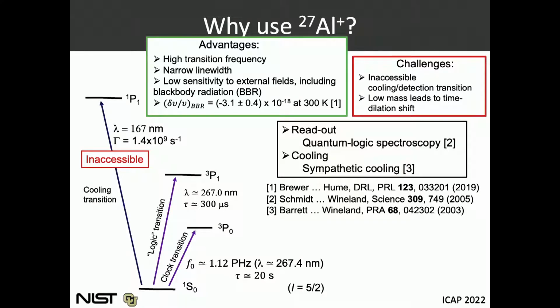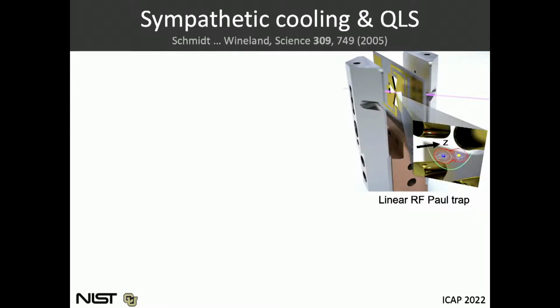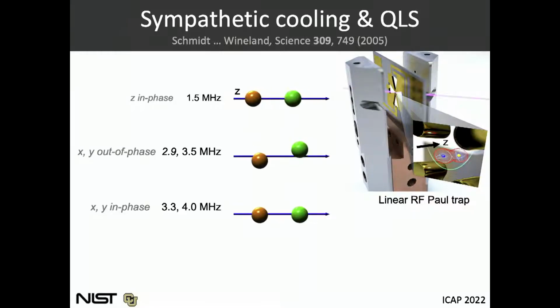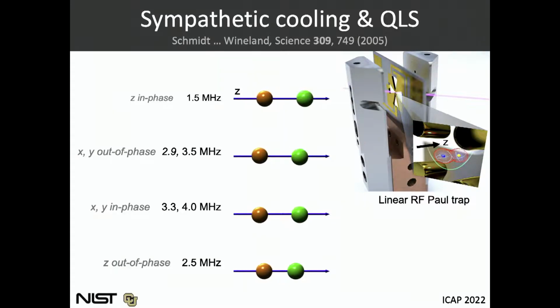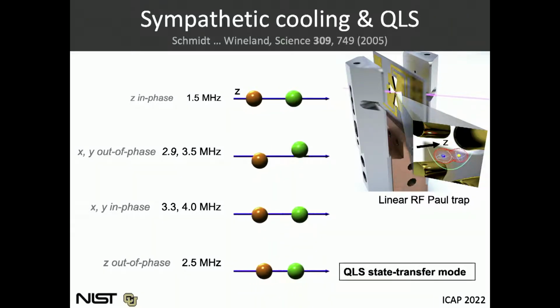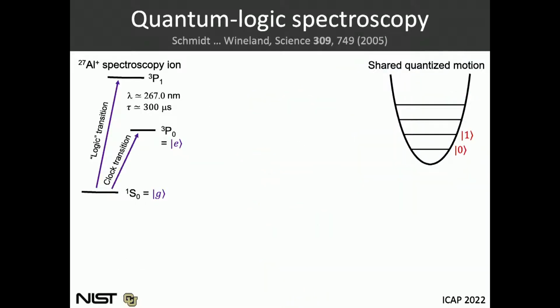Instead, we're using techniques from quantum information where we co-trap an aluminum ion here in the same trap with a logic ion that will be either magnesium or calcium for the clocks I'll talk about today. And because these two ions are both positively charged, their motion is strongly coupled, and we can laser cool the magnesium in order to cool the motion of both ions. And furthermore, we can use these motional modes, which are quantum degrees of freedom, to read out the internal state of aluminum. And that's using a technique called quantum logic spectroscopy.